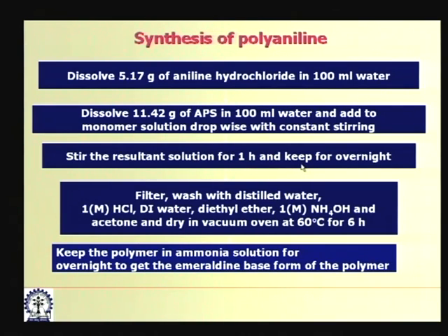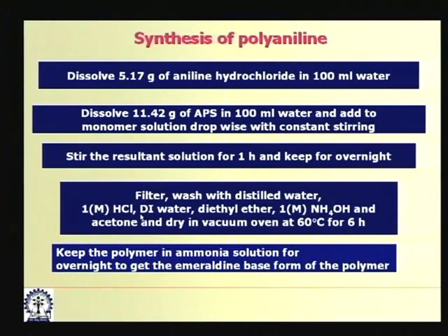Say after 12 hours of stirring, this precipitated polymer is to be filtered, washed with distilled water, then with acid in order to remove any unreacted monomer aniline hydrochloride, followed by deionized water, followed by diethyl ether, and finally with ammonia solution, then acetone in order to remove water before drying.